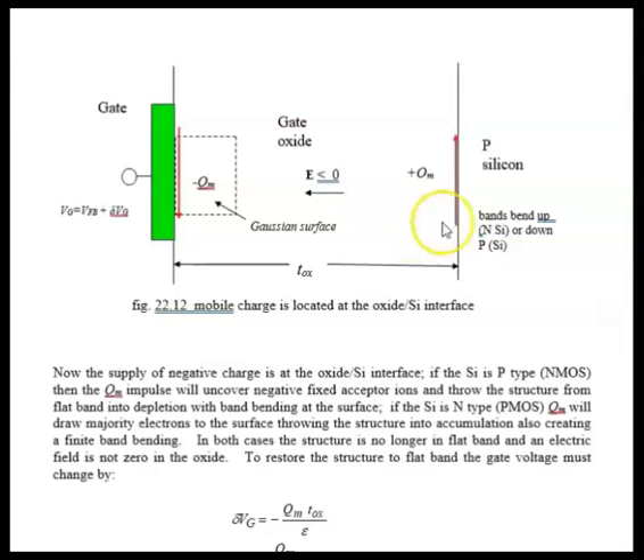And the problem revolves around this interface, the interface between 2 different materials, in this case silicon and oxide on the left. Whenever we either grow or deposit one material on top of another, all kinds of dangerous things can happen. Specifically, we can have contaminant atoms which come into the growth process or the deposition process, or we can have dangling bonds which don't have counterparts. In this specific case, we'll have dangling silicon bonds which are not filled. So we can have what we call trapped or interface charges right at this interface.